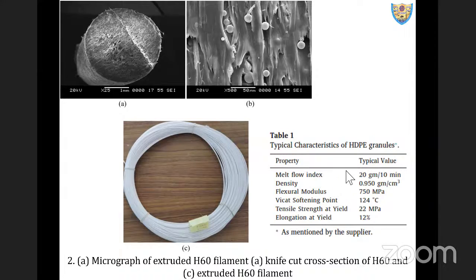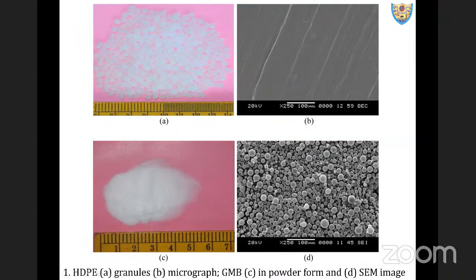20, 40, 60 are the numbers of glass microballoons, or reinforcement or filler, by volume in HDP. And the H is from HDP. So that's how we denoted it as H, capital H for HDPE, H20, 40, 60. Once we blend this, the pellets of these foams are dried at 80 degrees C in an oven for 24 hours before gravity feeding into the hopper of a single screw extruder. I've shown that to you as well. The quality of extruded filament depends on the extrusion system parameters. What I mean by that is barrel temperature, die temperature, screw speed, and takeoff speed.